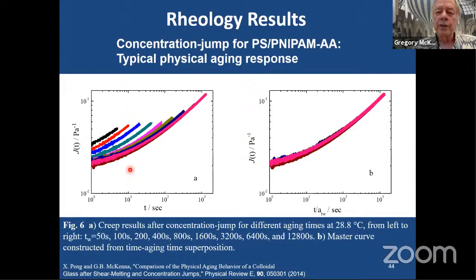So, okay, this is rheology in a concentration jump for a thermo-responsive colloidal particle. And so we do a jump, we change concentration, and we watch the creep response of the material as it ages, and we get aging time superposition. And here's the master curve. So the curves have the same shape. And from that, this is for aging from 50 seconds to 12,800 seconds. And it had stopped aging by the time we were there.